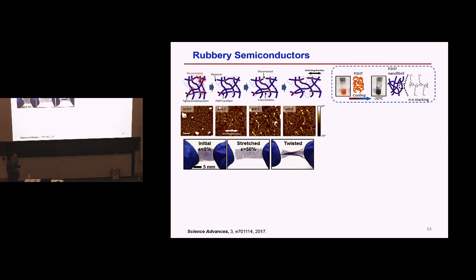We actually designed a material system. We tried a lot of options, and eventually the organic semiconductor percolated composite worked out. Specifically, the material is a double interpenetrating network. The dark nanofiber structures are interpenetrated into the rubber matrix of polydimethylsiloxane. When you mechanically stretch these structures, for example up to 50%, we do observe many disconnections, but you still retain a lot of connection to allow the carrier to hop from one fiber to the other. Eventually, you can retain the semiconductor properties.